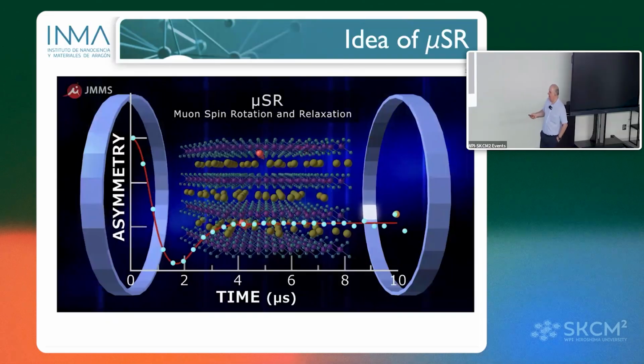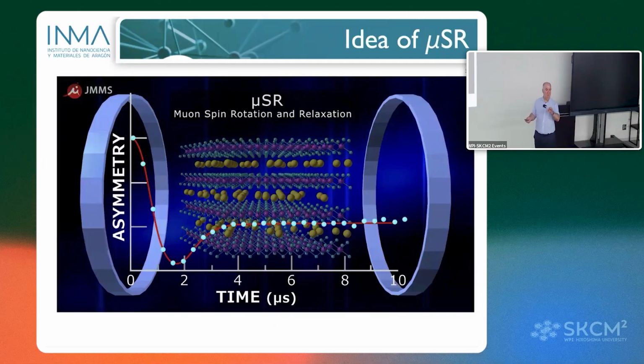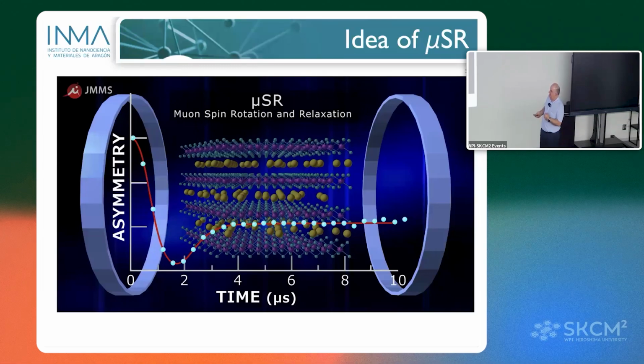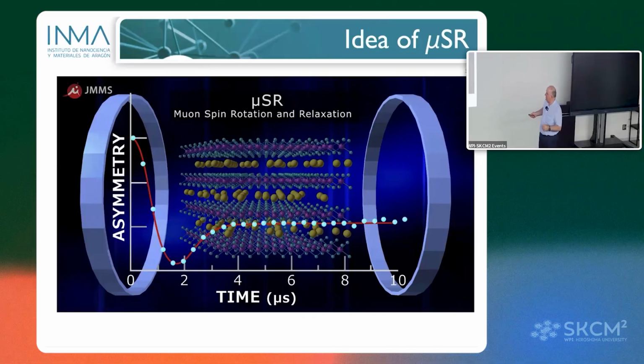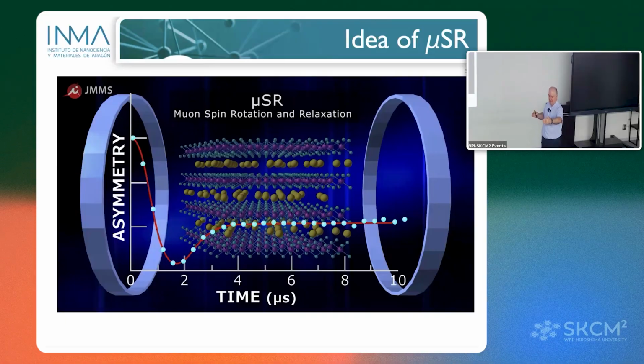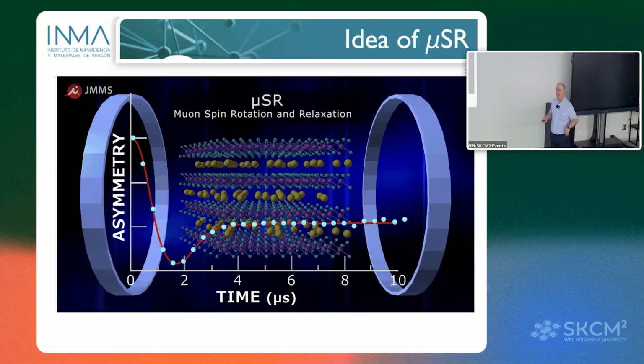But the muon, before decaying, is precessing along the magnetic field distribution in the position where the muon is implanted. When it decays, this precession means that the positron coming from the decay is not emitted the same in one direction as in the other. The number of positrons going in one direction is different from the number going in the other direction. If I put two detectors, one in front of the other, up and down, forward and backwards, left and right, I can see different asymmetry functions that are related to the magnetic field distribution in the point where the muon was seated. This is the idea.